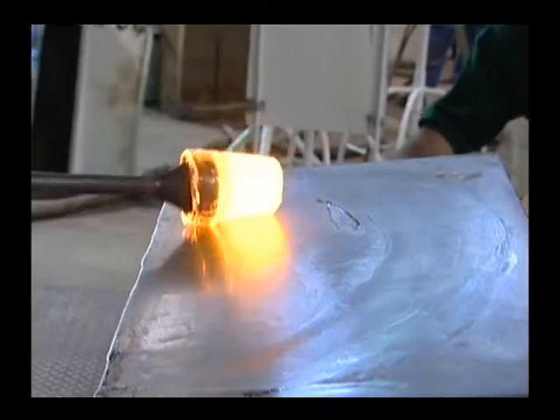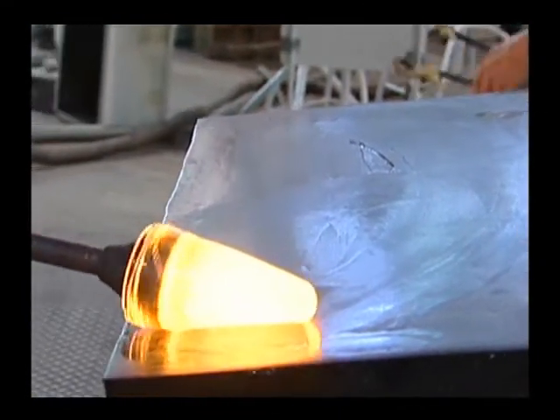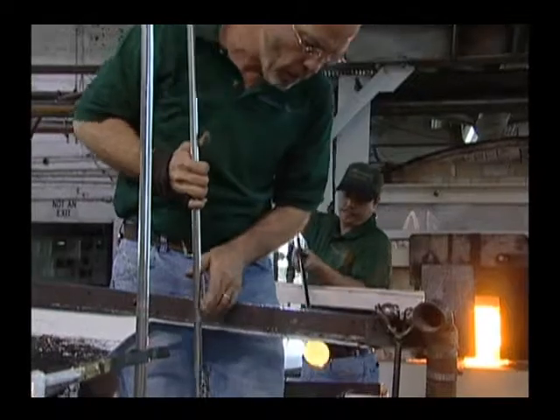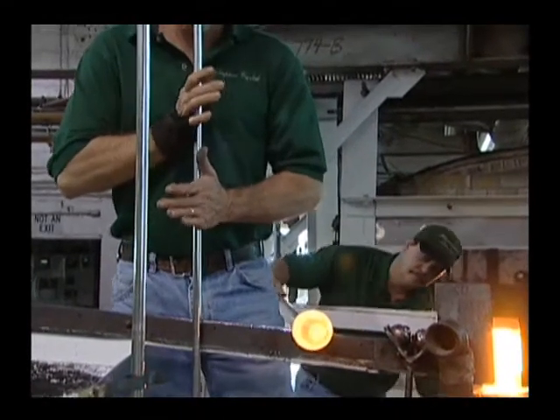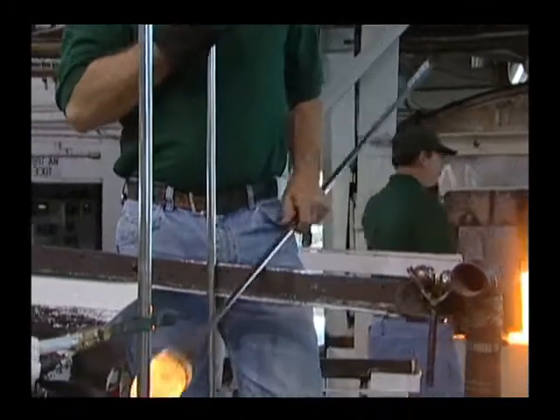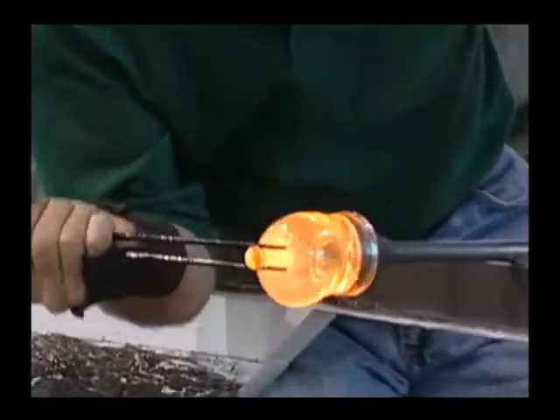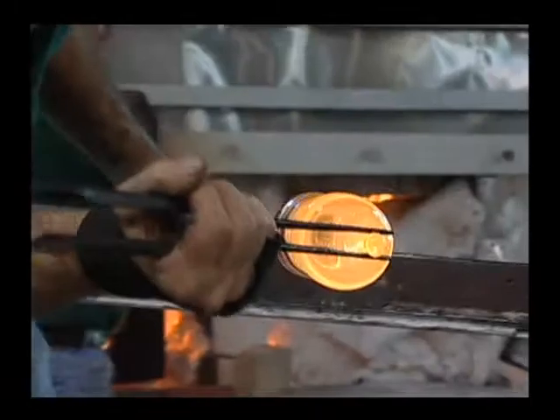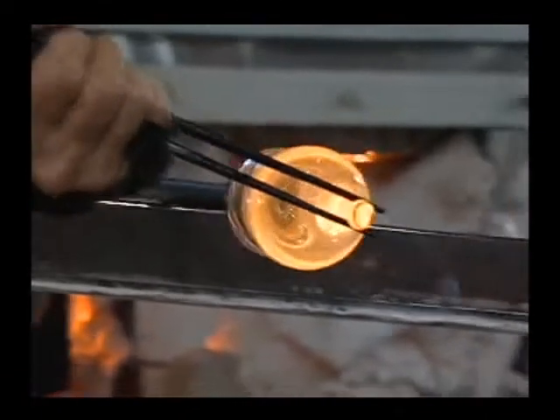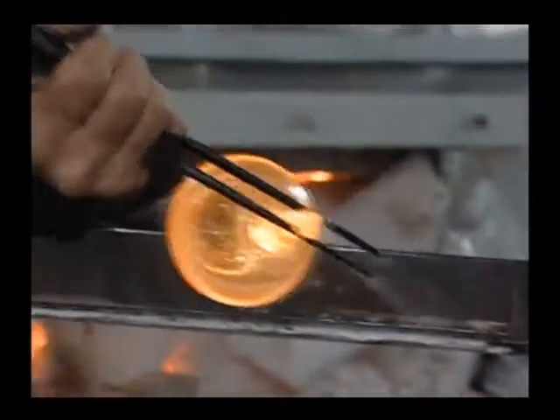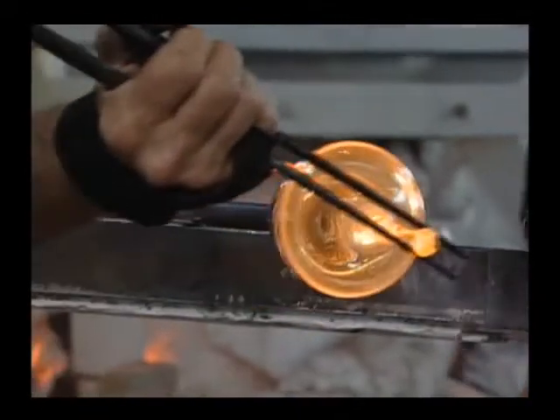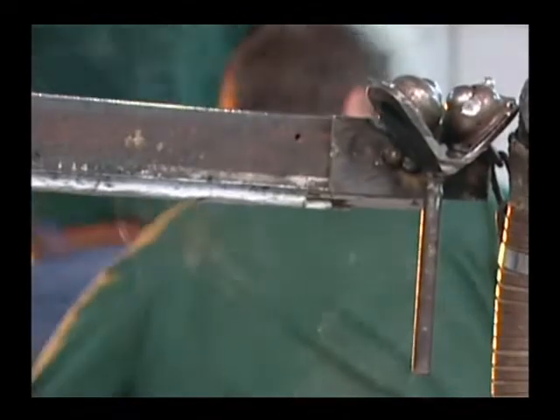A gatherer extends the blowpipe into the flaming furnace and gathers the correct amount of glass without generating bubbles or other defects. While constantly rolling the pipe to preform and cool the molten mixture, the gatherer passes it on to the blower, who continually rotates the pipe to keep the glass centered and to prevent the glass from running off the blowpipe. The artistic magic then begins as the blower first cuts a button which will allow for a glass stem to be pulled. Since the glass is cooling and hardening very rapidly, the blower only has one opportunity to make the stem before the working range of the glass is exceeded and the glass is frozen or set up.